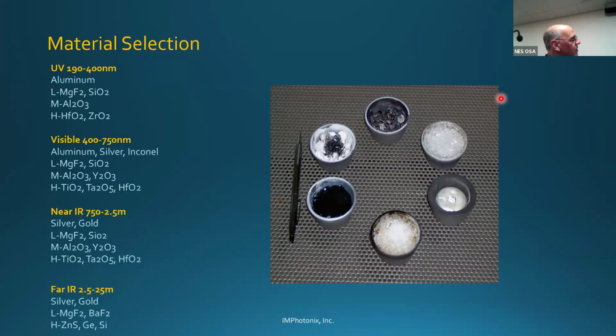Okay, so these are the different materials. When I talk about dielectric films, these are films that have different indexes of refraction. And we break up the materials into the spectral ranges that we want to use them in. This is not a complete list, but these are the most common materials that we use for the wavelength bands that we're usually supplying customers with. So for the UV, low index, 1.386, 1.45, magnesium fluoride then SiO2. Aluminum oxide is more of a middle index of 1.62, and hafnium dioxide and zirconium oxide are roughly 1.95 to 2.0 index of refraction.